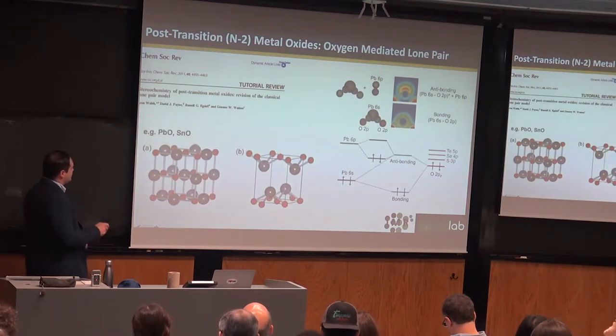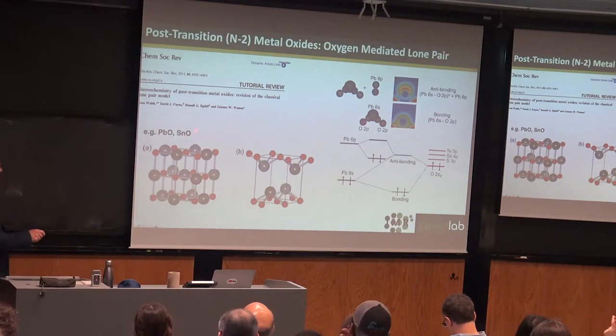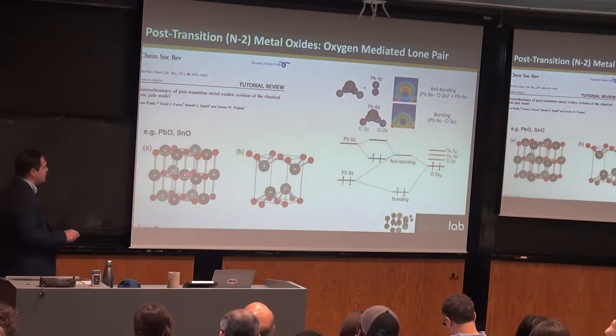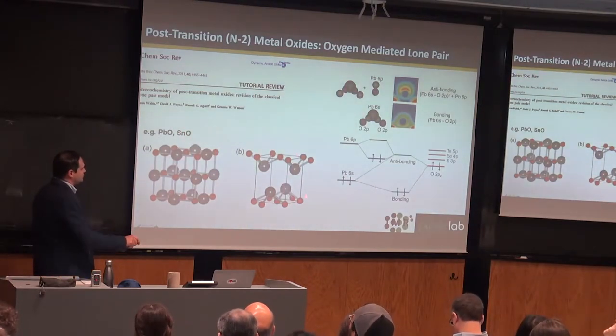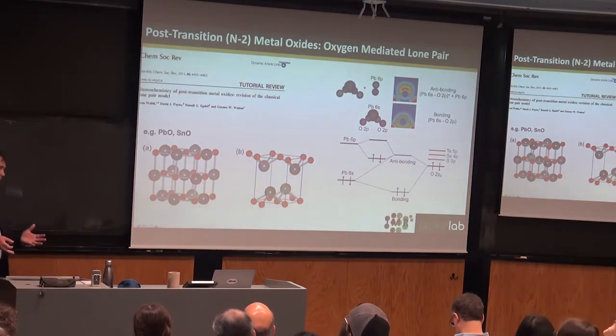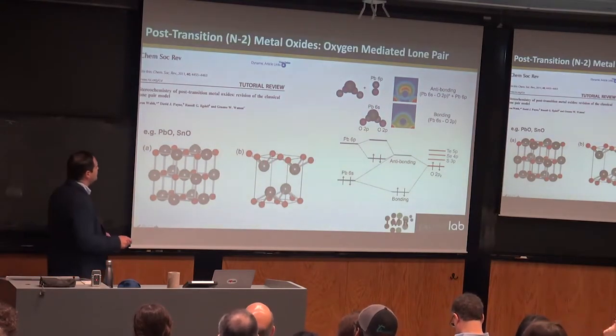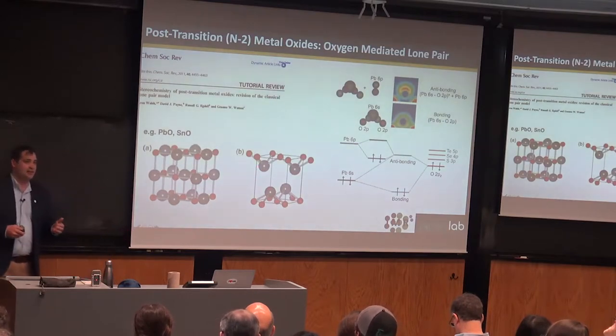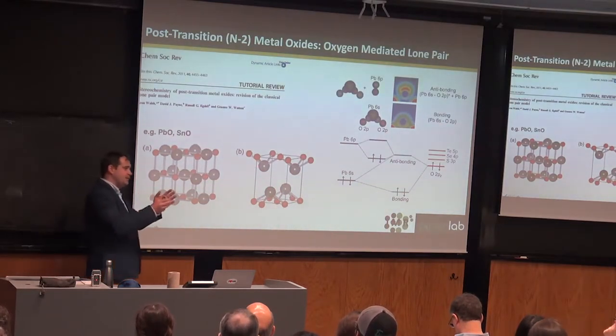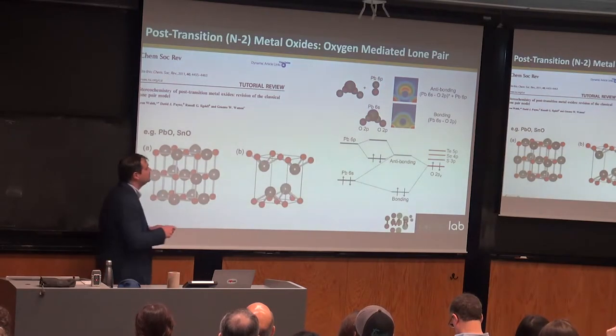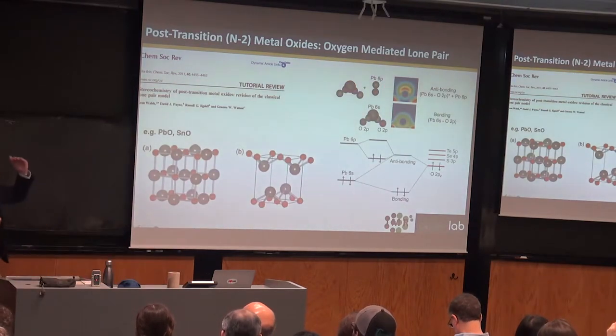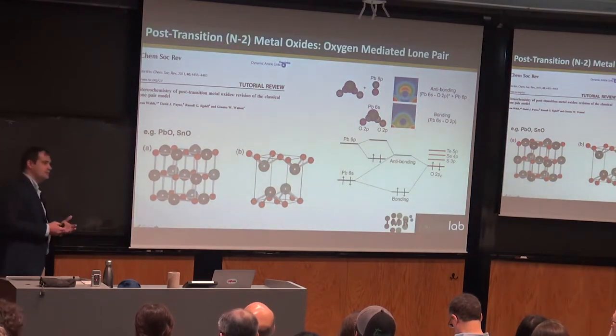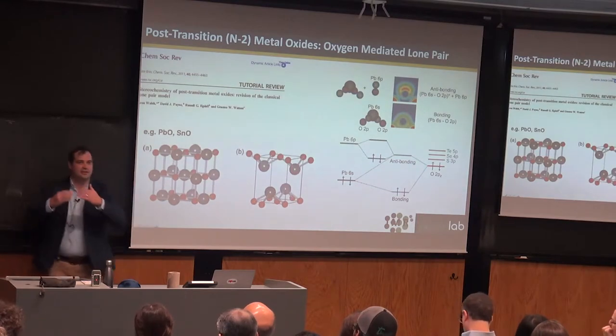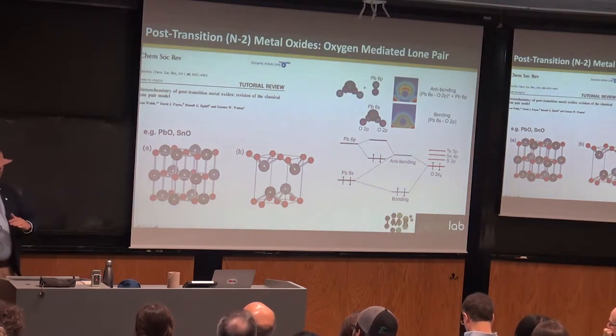So we knew from their structures, like things like lead oxide, tin oxide, where they were in the lower oxidation state, we knew that they preferred these more distorted structures, signatures of lone pairs. And so in those cases, they knew that they must be lone pairs. That means there must be metal s-p hybridization to form these lobes, and that would mean that the s orbital must be close to the unoccupied p orbital. But when they started doing the computational chemistry, they started to say, well, in my calculations, my s orbital is below my oxygen 2ps. How am I facilitating these lone pairs?